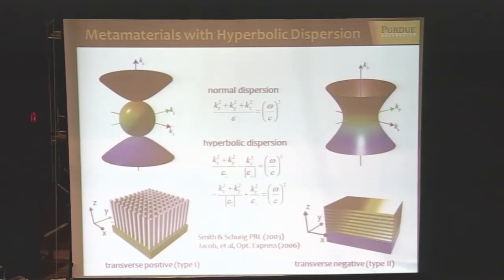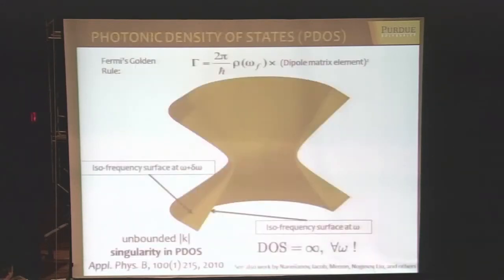The idea is that for conventional materials, if you draw the isofrequency surface in K space, for an isotropic homogeneous material you get a sphere. If it's anisotropic, you have a spheroid. And if in one of the directions epsilon is negative, so that your metamaterial acts like a metal conductor in one direction and a dielectric in another direction, then you get this hyperbolic surface. It's open, meaning you have unlimited access to very large values of K. That enables applications like a hyperlens. But most importantly for this discussion, if you look at the photonic density of states by examining the volume between two isofrequency surfaces, this frequency omega and omega plus delta omega, it's unlimited - it diverges.